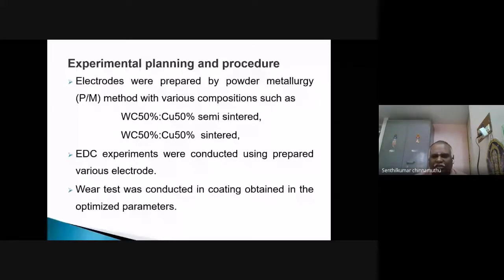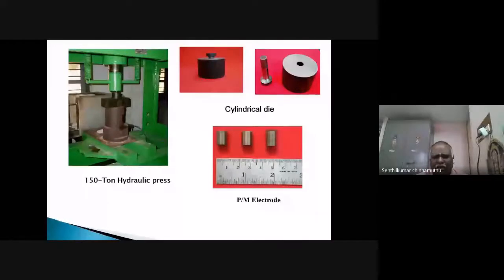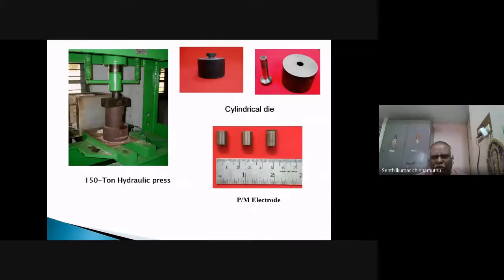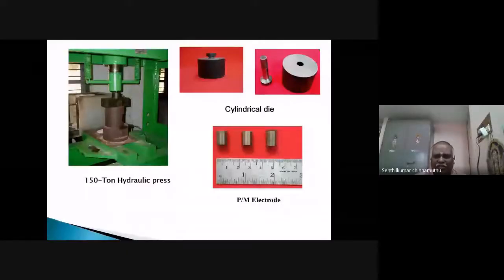See, the figure shows the cylindrical die which is used for preparing the powder metallurgical electrode, and this is a 150-ton hydraulic press which is available in the Department of Manufacturing Engineering in Annamalai University, with which we prepare the green compact. 50% of tungsten carbide and 50% of copper powders were mixed in the double cone mixer to get the proper mixing. The double cone mixer rotates at 300 RPM, and the time taken for this mixing is 30 minutes, which is taken from the literature to get the proper mixing.